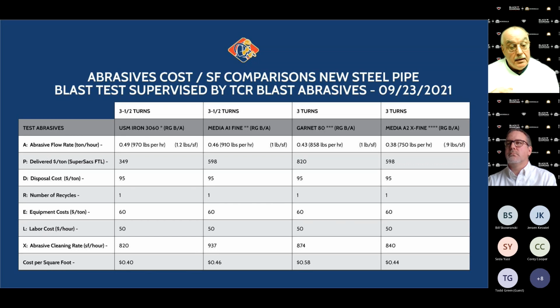And then given the abrasive cleaning rate, which is the second to the last line, 820 square feet per hour, 937, 874, 840. So those were extrapolated from the times and the amount of material that we have on there to give a cut rate per hour. Plug those all into the formula, and even though the U.S. Minerals Iron was a little bit slower and we used a little bit more, given the price per ton, it's the lowest cost per square foot. As you can see, 40 cents per square foot versus 46 for the fine, versus 58 for the garnet, versus 44 for the extra fine. So I know we went through that pretty quick, but that gives you a quantitative analysis